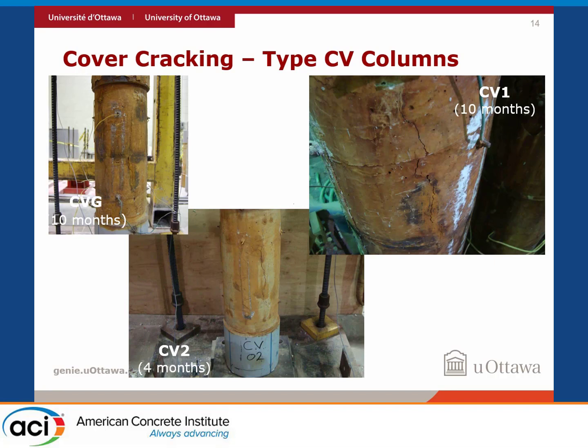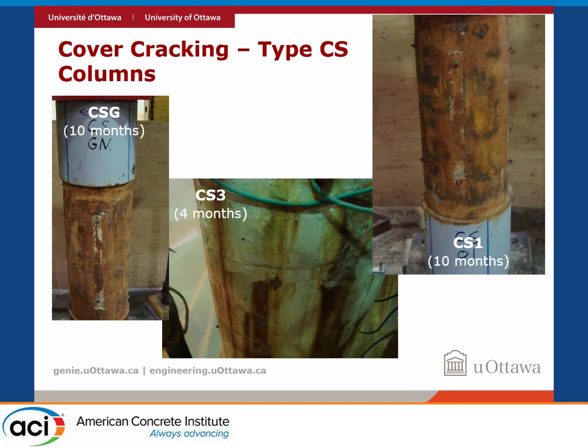For columns where the longitudinal reinforcement was corroded, it was very clear that cracks were forming along the longitudinal reinforcement. You see bigger cracks for those that were corroded for a longer period than a shorter period, but in general, the cracking pattern followed the direction of the longitudinal reinforcement. For columns where only the spiral reinforcement was corroded, the cracking was a little more random, but it usually followed the direction of the spiral. And we will see with the measurements now that the cracking was actually much smaller.